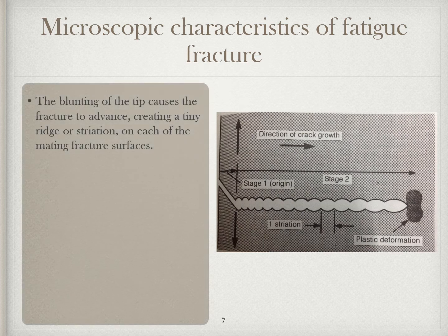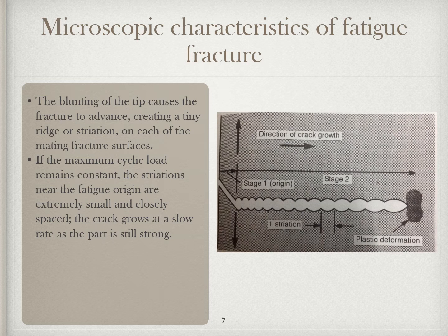If the maximum cyclic stress or maximum cyclic load remains constant, the striations near the fatigue origin are extremely small and closely spaced, as the crack grows at a slow rate because the part is still quite strong. So here we see in this figure these striations, they are very closely spaced. Here somewhere is the origin, and these striations are closely spaced, and further away they are widely spaced. However, as the crack gradually propagates, the spacing between the striations increases and the crack grows at an increasingly rapid rate because the crack greatly weakens the section. Eventually, complete fracture, that is stage 3, and separation occur.